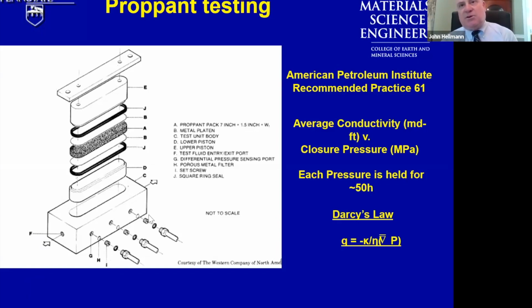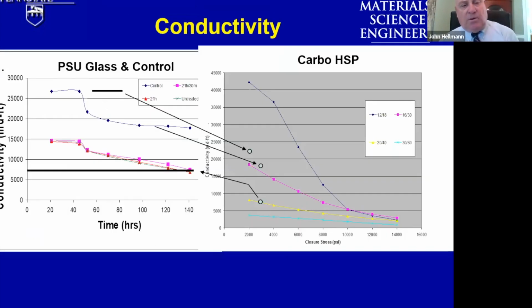Using this, and using Darcy's law, we can calculate the permeability of that packed particle bed as a function of the uniaxial load. And that will tell us how useful that particular proppant particle type is for use in stimulating oil and gas wells. These are some of the results that we achieved, and basically what we found is that the ion exchange glasses perform admirably well.